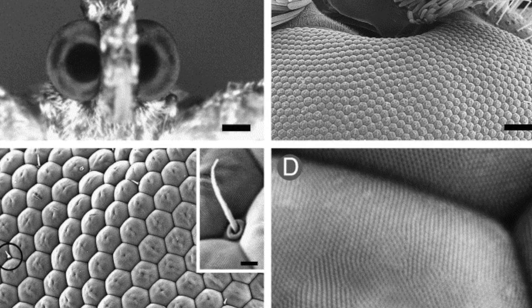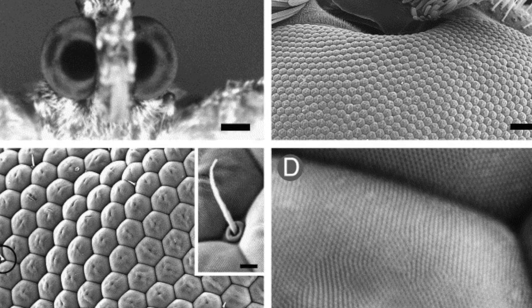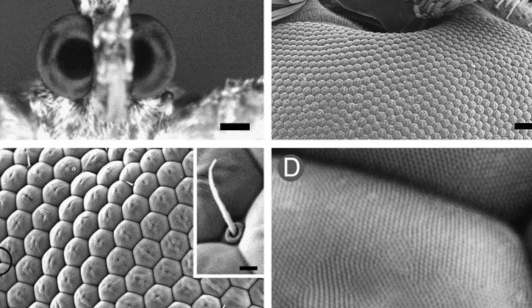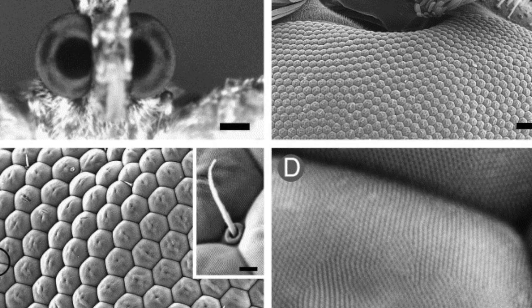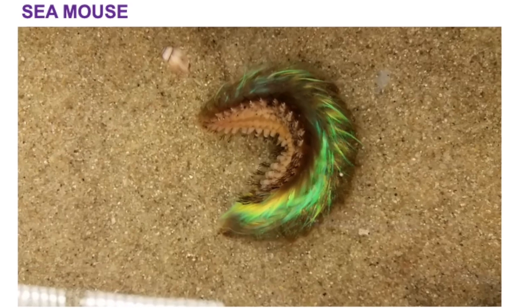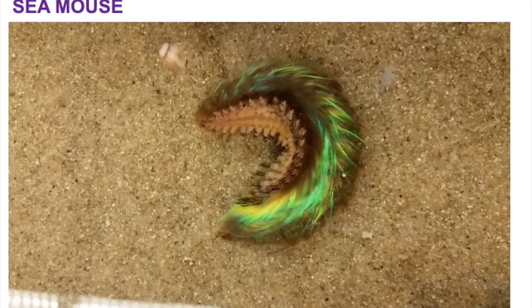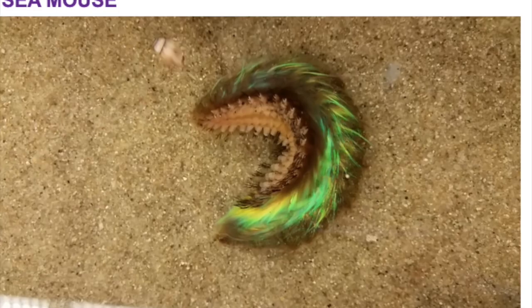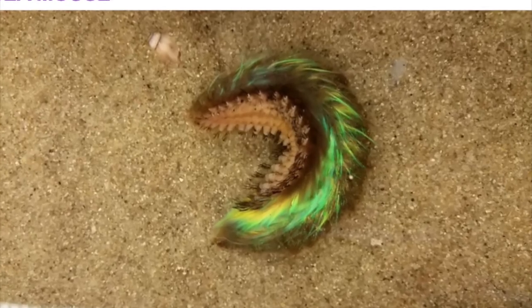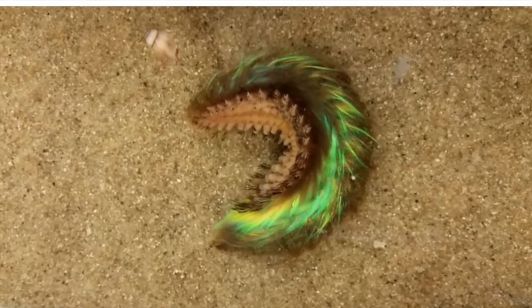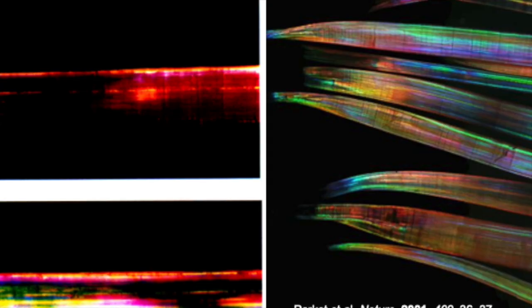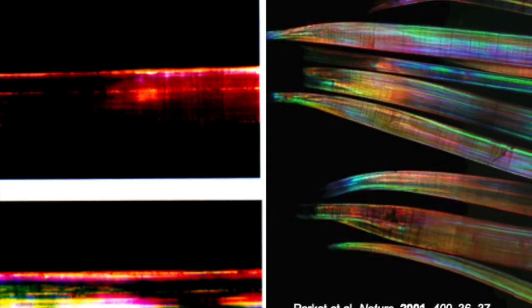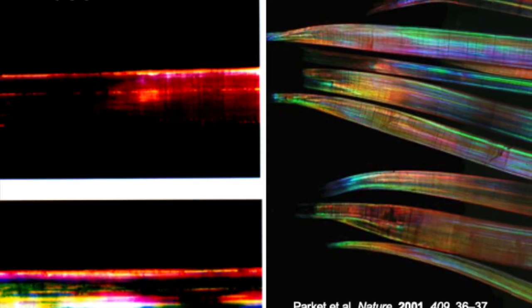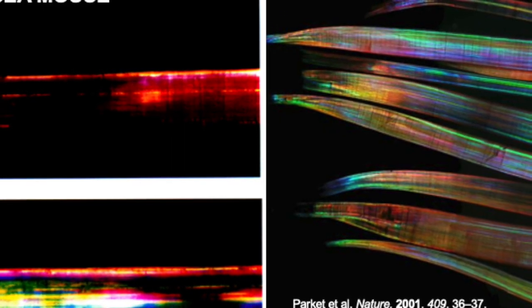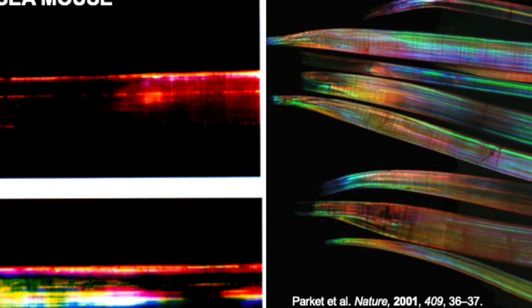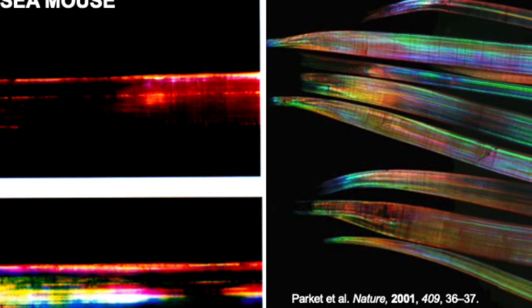In addition, these 2D gratings can also exhibit self-cleaning capabilities, owing to the high fraction of air trapped in the trough regions between the arrays. Researchers have discovered and characterized a two-dimensional photonic nanostructure in the hairs of the sea mouse, which consists of periodic long fibers. Each sea mouse hair contains thousands of hollow, close-packed, longitudinally oriented cylinders with diameters of about 230 nanometers. Bright structural colors are produced when these cylinders collectively diffract light incident on the side of the hair fibers.